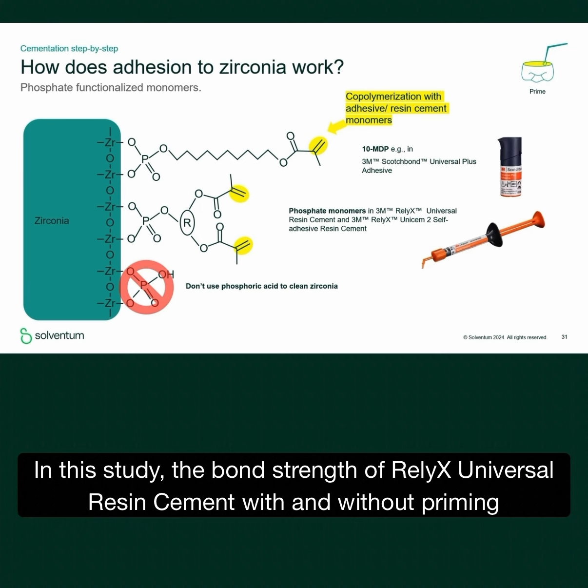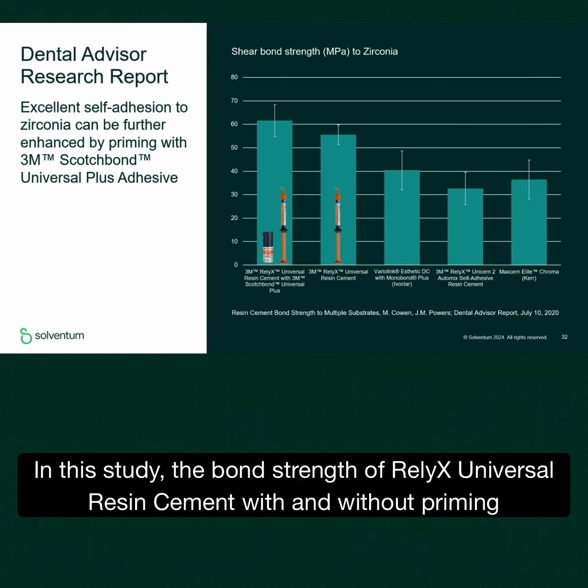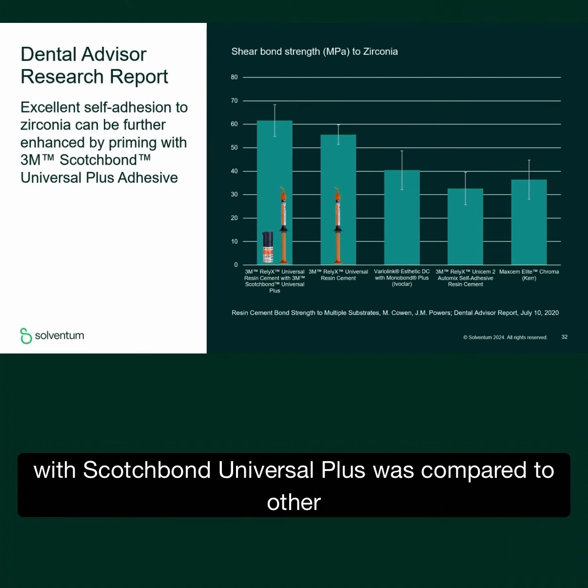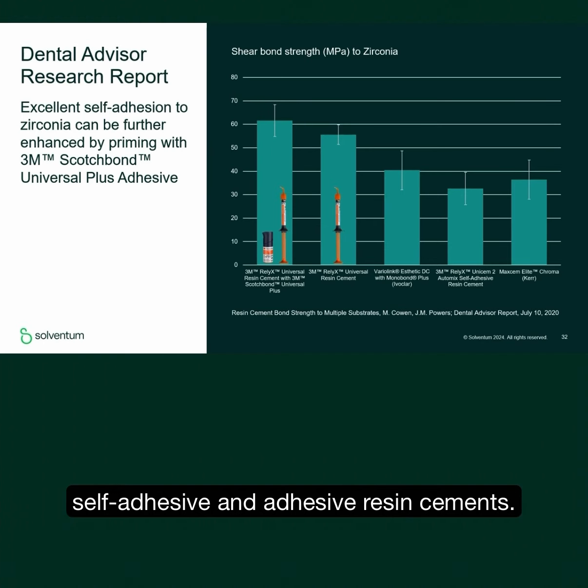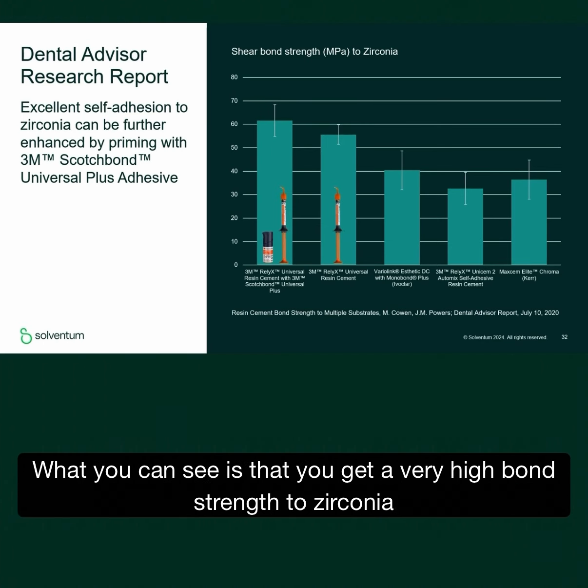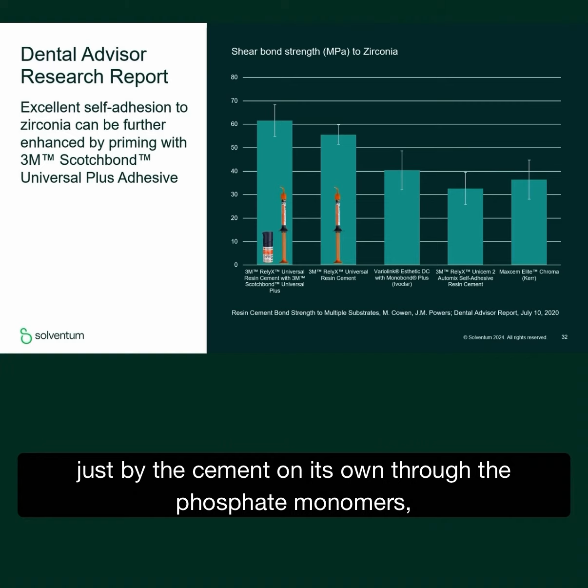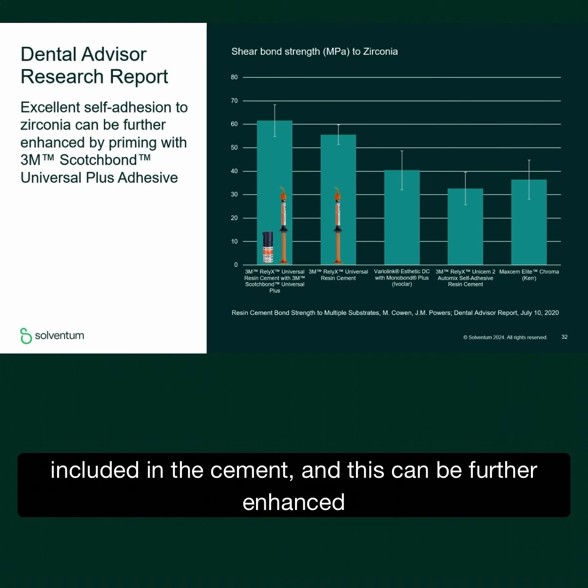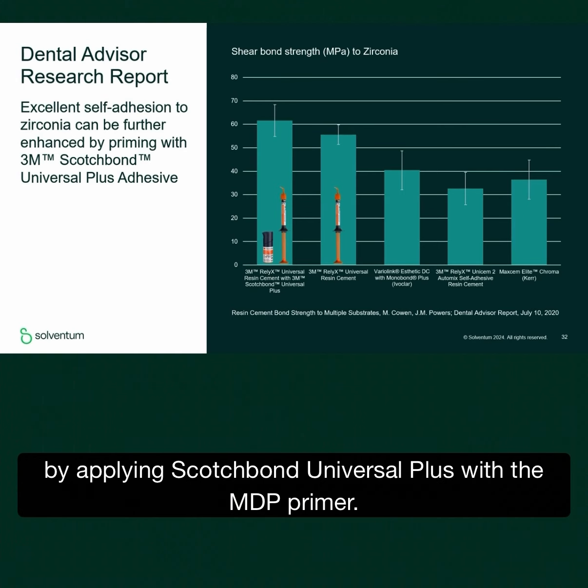In this study, the bond strength of Relyx Universal Resin Cement with and without priming with Scotchbond Universal Plus was compared to other self-adhesive and adhesive resin cements. What you can see is that you get a very high bond strength to zirconia just by the cement on its own through the phosphate monomers included in the cement, and this can be further enhanced by applying Scotchbond Universal Plus with the MDP primer.